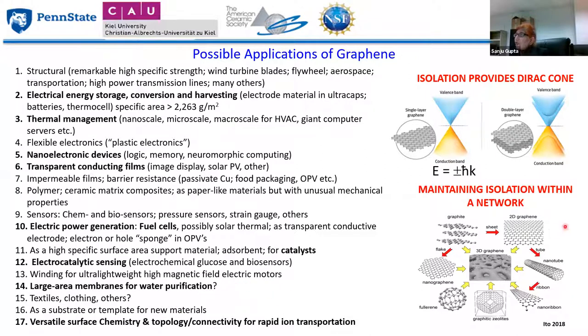Here we know the classic graphene, which has what we call the Dirac cones, with a linear dispersion. But in order to maintain this cone and have all of these superlative properties, it's not easy, and that's why people are doing research. So how do we maintain that isolation, in other words this Dirac cone, the high electronic density and many other applications in a 3D graphene system? When we start to stack the graphene, first we peel the graphene off, and then we stack them back to make the 3D graphene, which is a challenge.